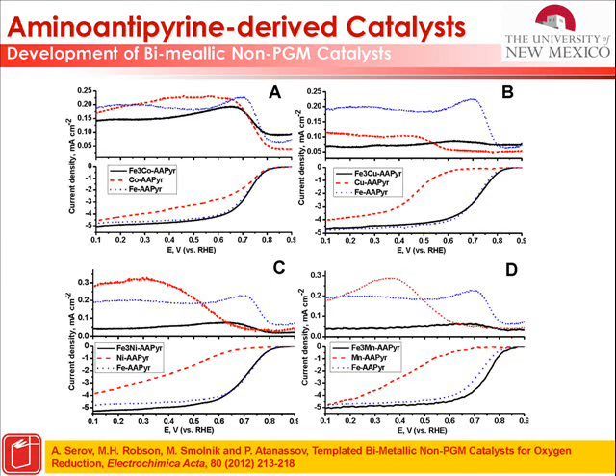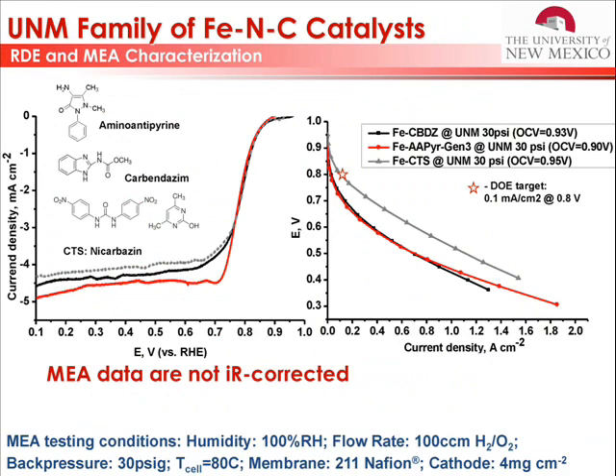And we mill it with iron nitrate to a powder the same way we make cement. And then we fire that powder. And that catalyst was the best. The catalyst was made without any dissolution, without any complex formation, but with a high stability of the ingredients, so they will withstand until 700, 800 degrees C, and only then start decomposing. So the high pyrolytic stability makes the best catalyst because it maintains the structure.